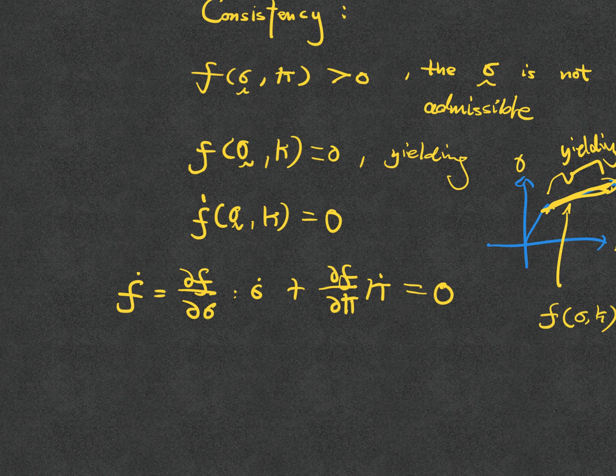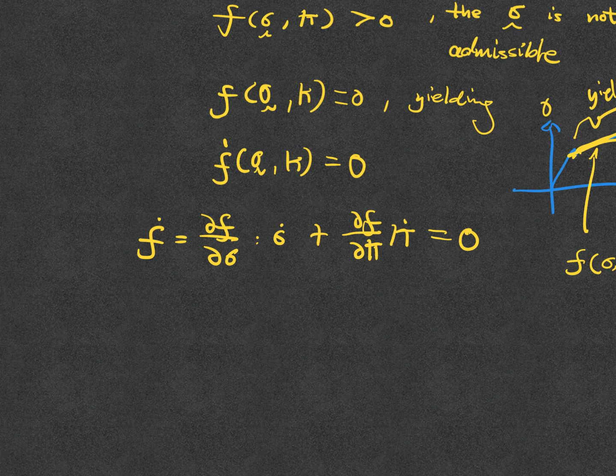Okay, so what is the physical implication of that? That means there's a governing rule on how the yield surface changes. Okay, so this seems very abstract, but I would say the following. What it actually means on the picture is that if I change my yield surface from the green circle to the yellow circle, and by the way, because this is a homogeneous function, the yellow circle and the green circle share the same center.